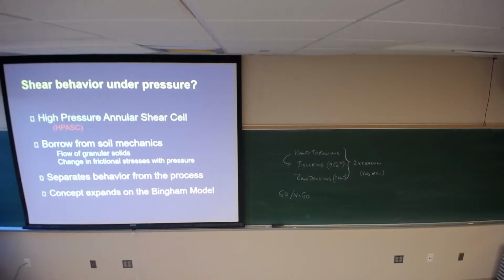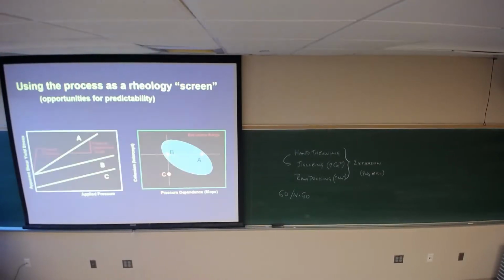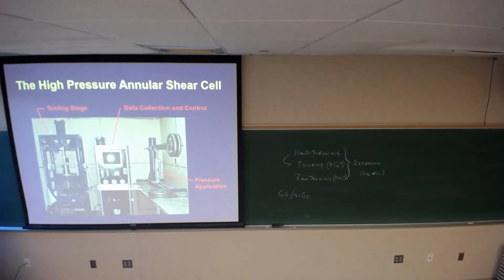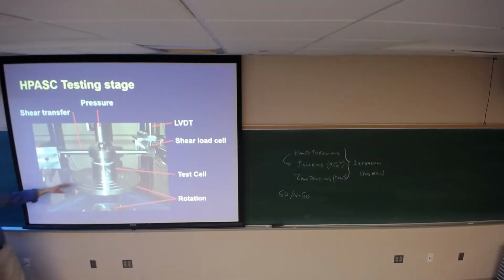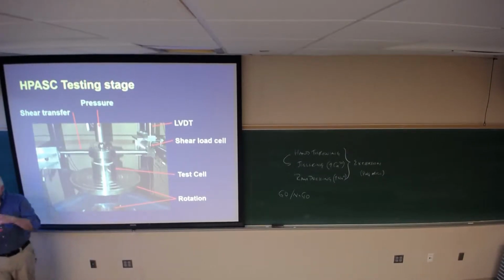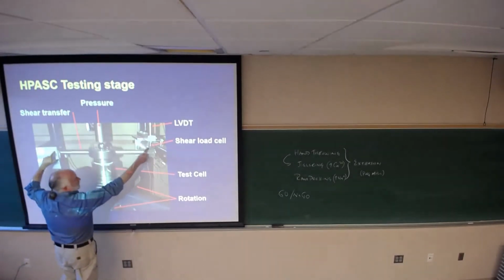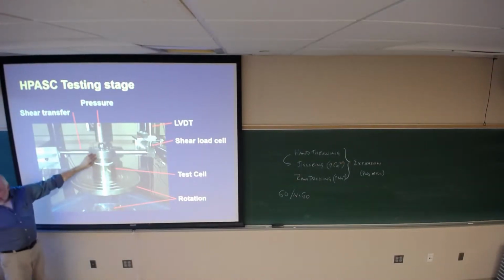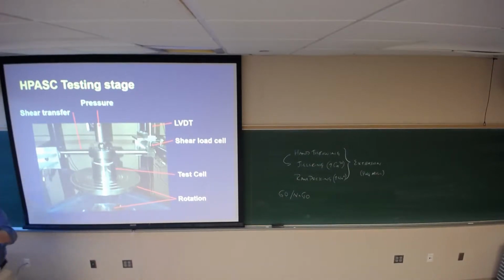We developed a high pressure shear cell. I'll show you a picture of it here. We developed this instrument basically. It sits in the lab still. We use it occasionally. What it is, you have an annulus, you put a material in here, you apply pressure on it, and then you shear it, right? You rotate it. This arm here has load cells to stop the top from turning while the bottom turns. So you're continuously shearing that material, and you're looking at the drag associated with that.